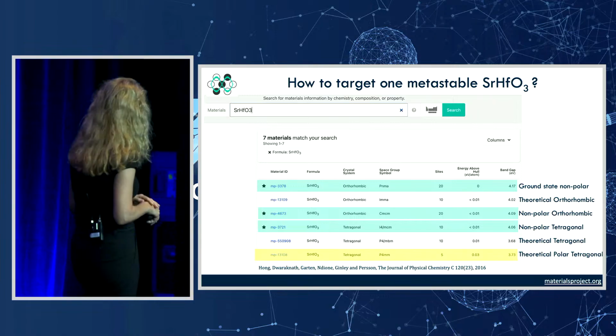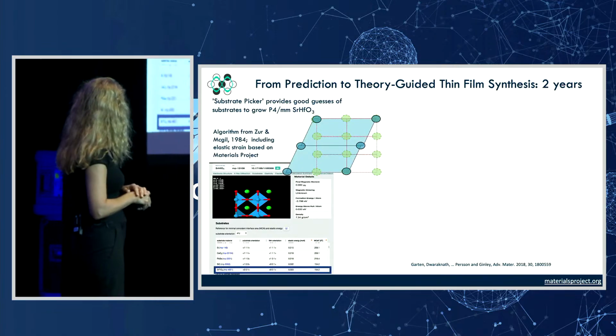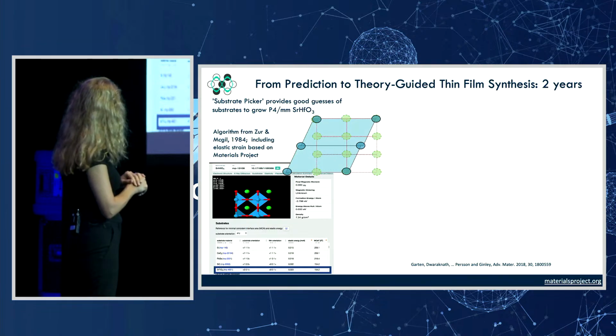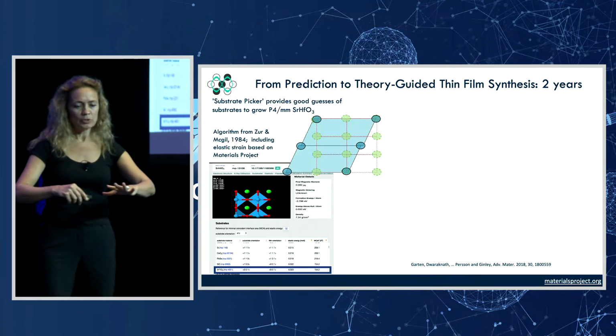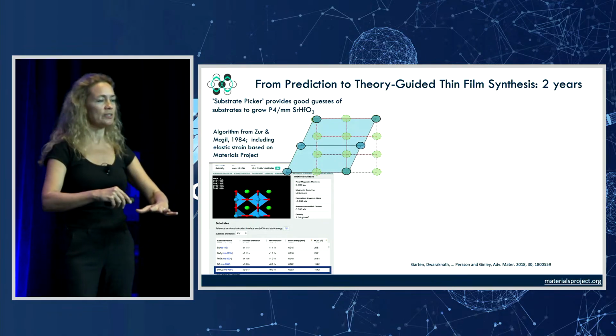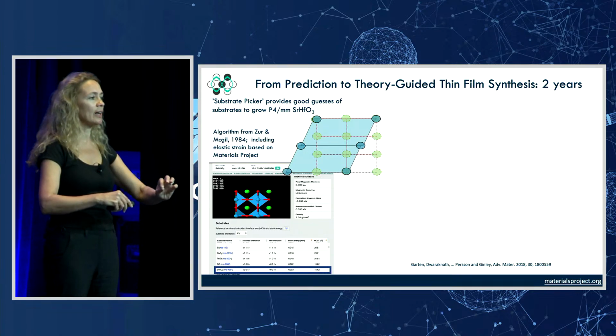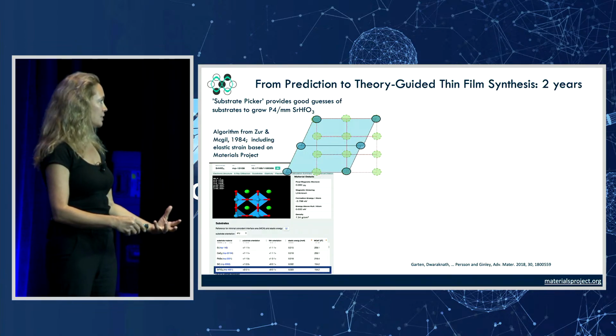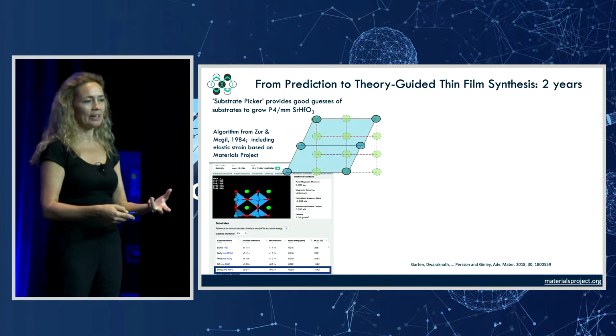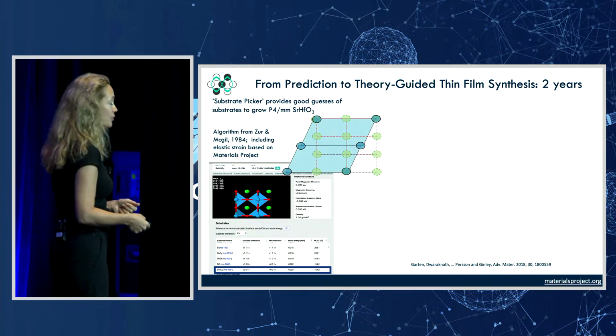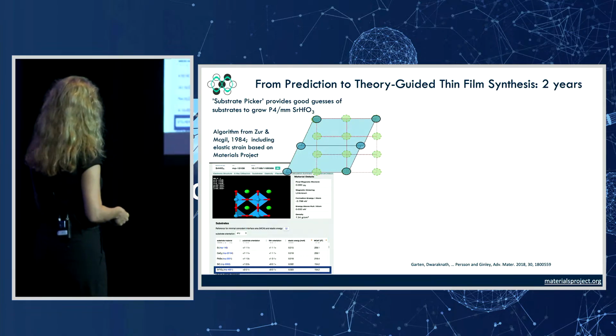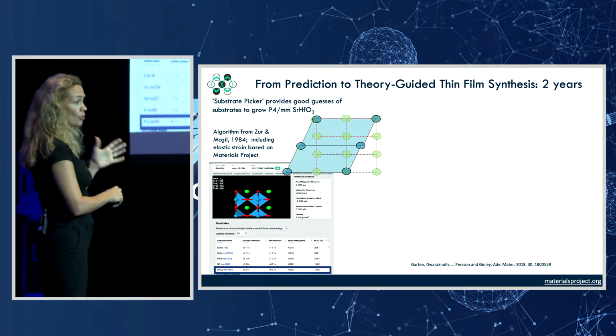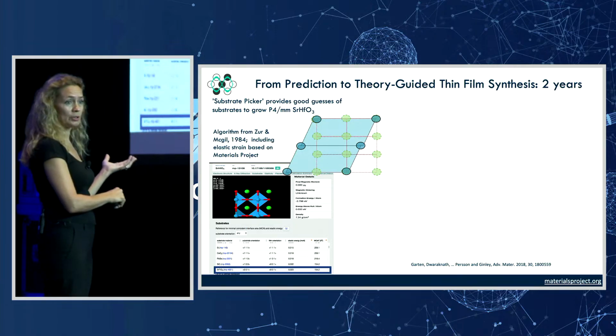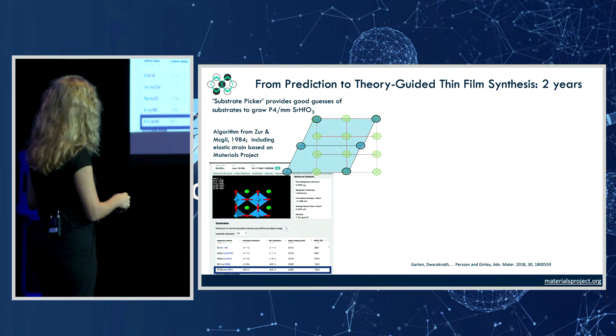So this is the guy that we were trying to make. We used an old algorithm from Zur and McGill from 1984 to design a substrate for thin film synthesis that would penalize other more low-lying phases of strontium hafnium oxide and promote by elastic strain and by the topology that particular polymorph. Just that algorithm, by the way, is now on the Materials Project. So if you are into thin film synthesis, you can use this and you can tune your own substrate.